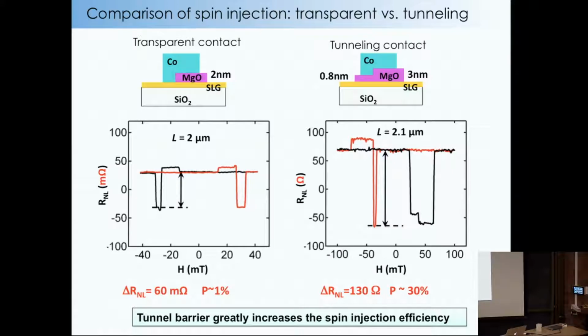And so we had this type of contact, which is a direct contact, and this kind of contact, which was a tunneling contact. We weren't even sure it was tunneling initially until we did some electrical measurements. What we find is that not only does the size of the signal in ohms change, going from milliohms up by 2,000, but you can also extract the spin polarization. It went from 1% to about 30%. The cobalt itself is somewhere between 30 and 40, so this is about as high as you can get without fancier tricks or fancier materials.